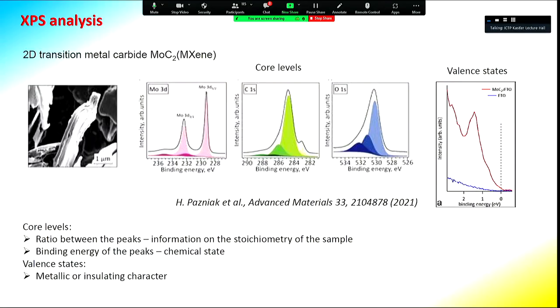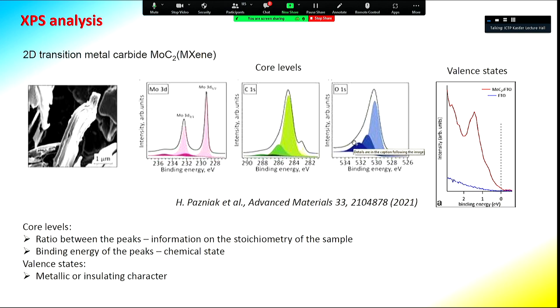XPS analysis can also provide useful information on samples. For example, in a study on molybdenum carbide MXene, two peaks related to molybdenum and carbon — the intrinsic elements of the MXene — allow estimation of the ratio between the two elements, checking whether there is excess carbon and whether the material synthesis was correct. One can also see adsorbates on top of the materials. Normally, core levels are fitted with different procedures to find different components from which you can understand the chemical state of the elements.